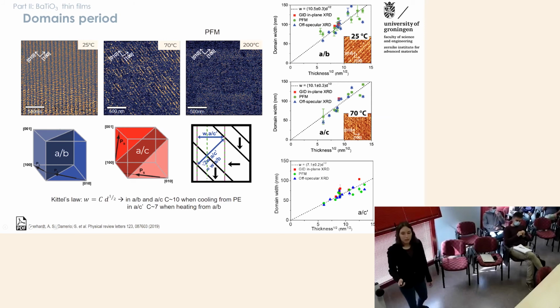But what is interesting is that when we measure the high temperature phase, not from cooling from the ferroelectric phase, but upon heating from the low temperature phase, we find that this prefactor parameter is now decreased to 7. And this is due to the fact that the domains of the new phase actually form on top of the position of the domains of the low temperature phase, because that's easier to nucleate in the pre-existing domain position. And this induces a geometrical constraint to the periodicity of the higher temperature phase, which is thus actually linked to the low temperature phase.